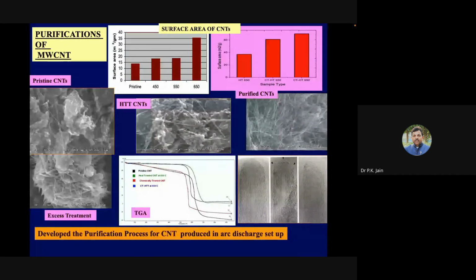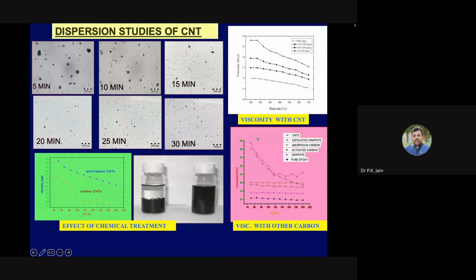Now, from here onward, dispersion issues will be taken up. Carbon nanotube, when synthesized through an arc discharge, has a lot of other graphitic or carbonaceous material which has to be purified. This purification requires steps of thermal treatment, mechanical milling, and chemical treatment, or a combination of all. And then only will you get highly purified carbon nanotubes. Now, if this carbon nanotube is not dispersed, it will settle down like this in a bottle. So it has to be dispersed. Then only can you find the applications.